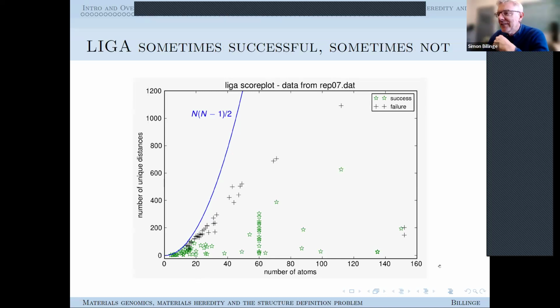But what Pavel did is he put it onto this plot, which separated it into 2 axes. And the second axis is the number of unique distances on the cluster. So you can imagine that if you have some number of atoms like 40, if it's forming a very high symmetry cluster, it's going to do that with a small number of unique distances. But if it's forming a very low symmetry cluster, it's going to take a large number of unique distances to specify the cluster. And so basically, when you go up in this direction, you're going down in symmetry. And if you have no symmetry, you have a completely random cluster, you're going to follow this curve here, which is n times (n minus 1) over 2, which is the number of degrees of freedom in that pairwise problem. So everything has to be below this blue curve.